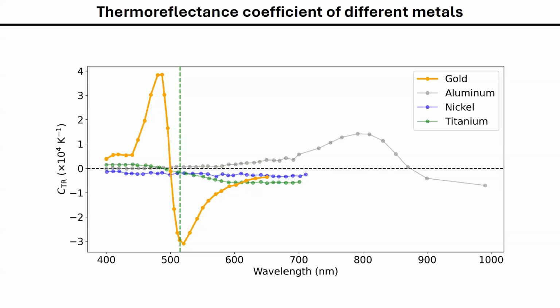So the reflectivity changes much more for the temperature increase. So in this case, as we are limited to these two wavelengths, we decided, let's switch it around. Let's use the green as our probe and the infrared as our pump. Of course, we started getting much better signal, and like a miracle, we started resolving all these thicknesses of our flakes, with some trade-offs, of course. But yeah, this was the main reasoning behind it.